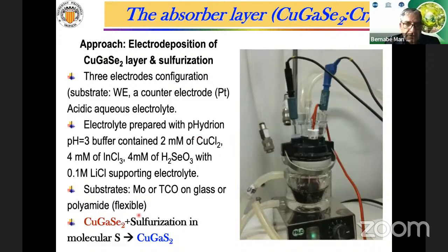As working with sulfur is quite difficult, we have produced copper gallium selenide, which is easier, and then proceed with sulfurization in molecular sulfur. So we produce copper gallium selenide electrochemically, and then after a process of sulfurization, we obtain copper gallium sulfide.